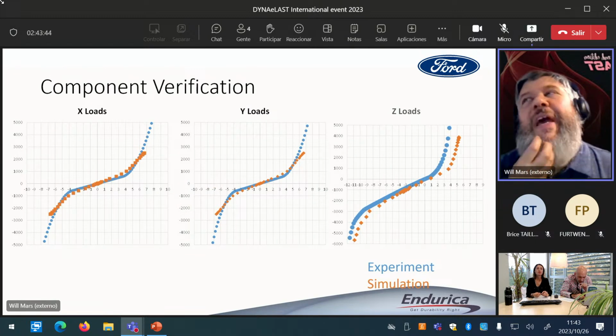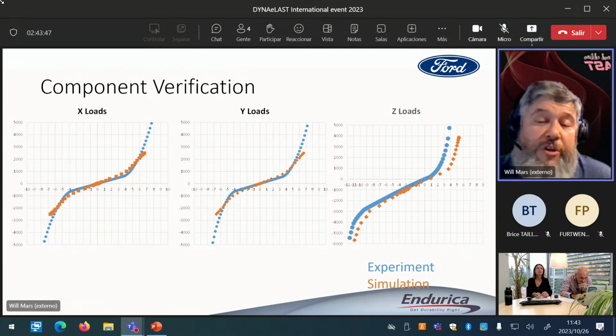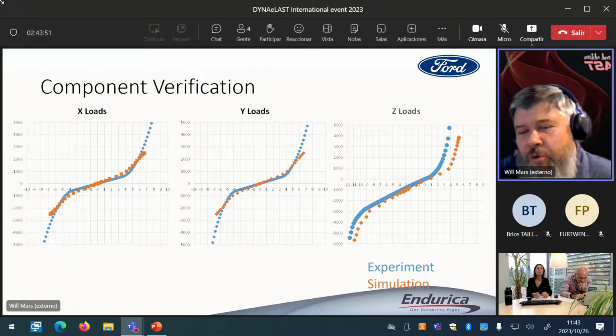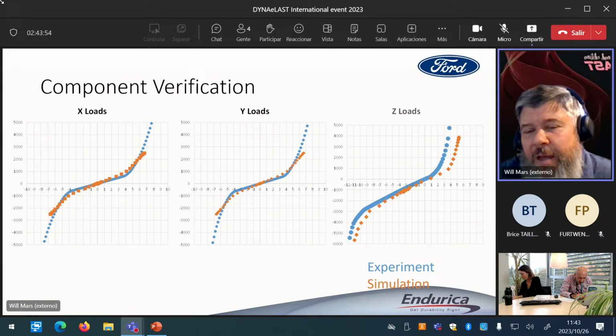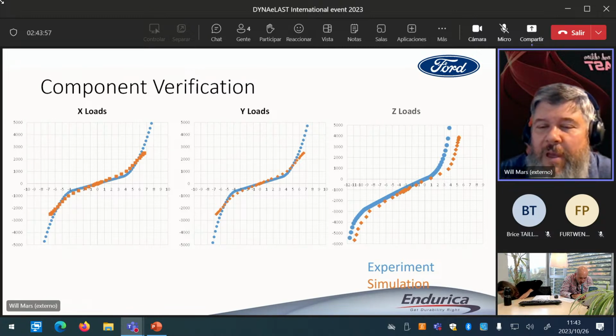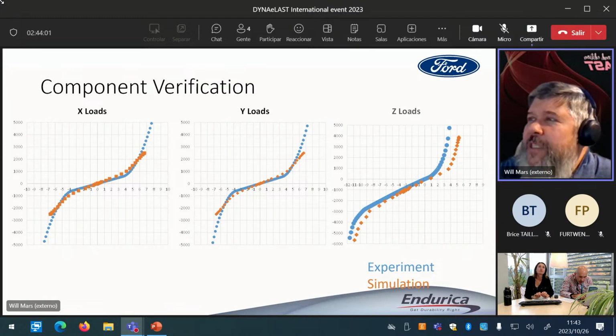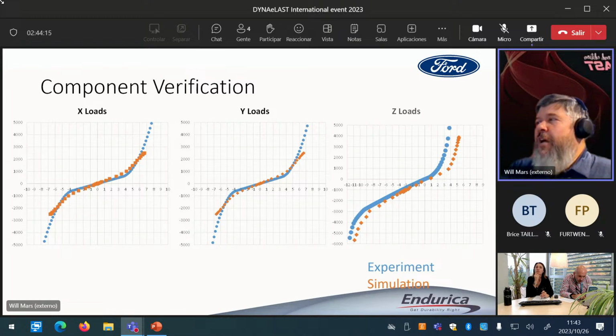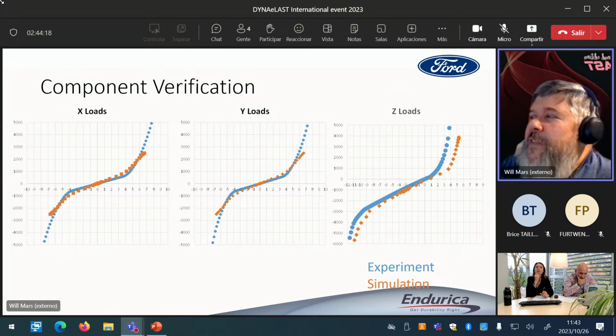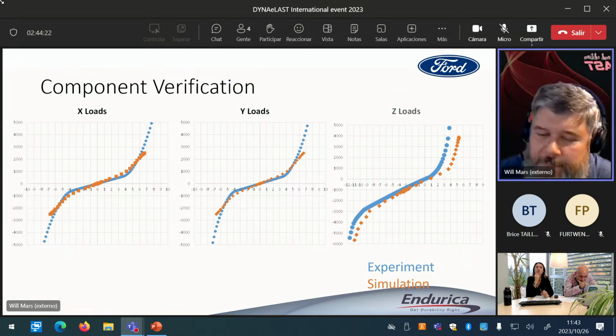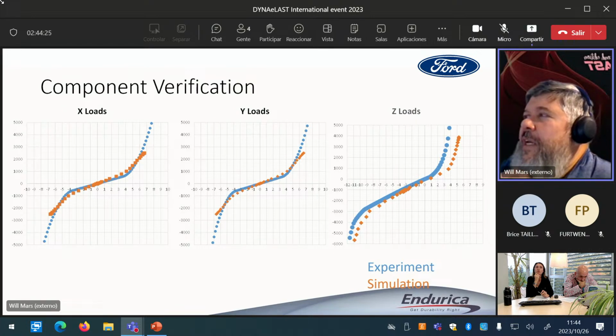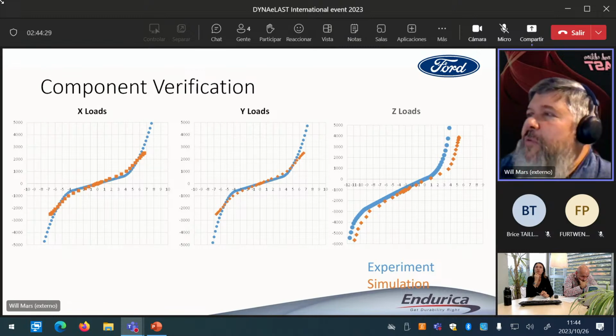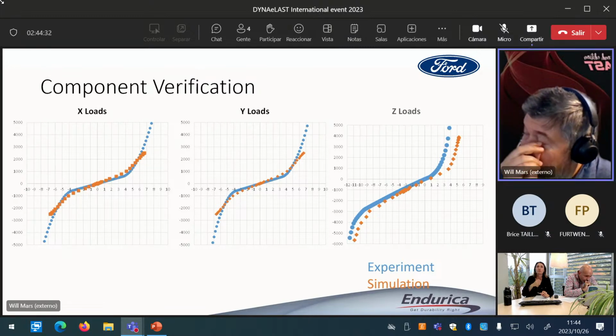Now, once we've defined the material behavior, before you do a fatigue analysis, you ought to make sure that your finite element model is behaving reasonably. Ford gave us experimentally measured load deflection curves for the X, Y, and Z axes. And here we've overlaid the results of those experiments with the results of our simulation. The experiments are shown in blue, and the simulations are shown in orange. And it's not perfect, but I think it's a quite reasonable agreement between the simulation and the experiment.